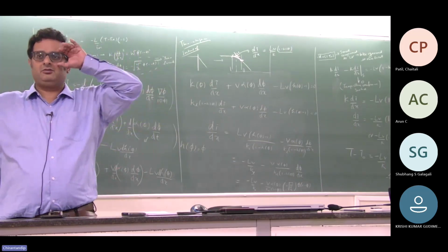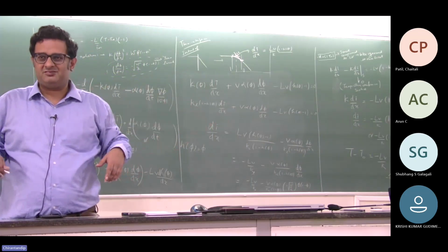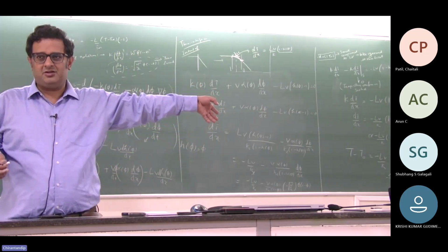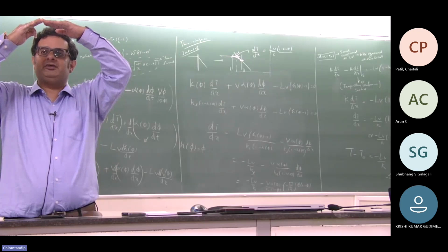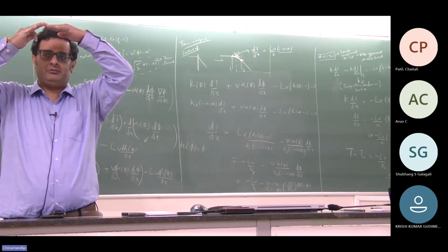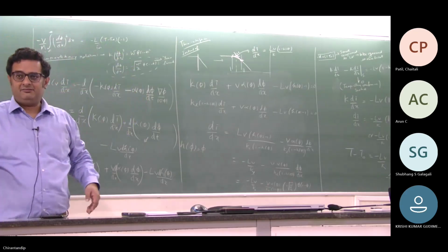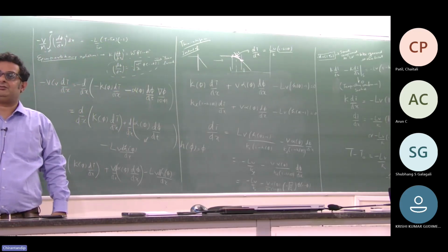Why are we correcting it via mu and not directly in the concentration? Because I'm writing a mu equation, just as I was writing a p equation before. The mu should be continuous, and mu having a jump corresponds to the effect, so I'm correcting for the mu jump. C will have a jump, but because mu has a jump, C will also have an extra jump.